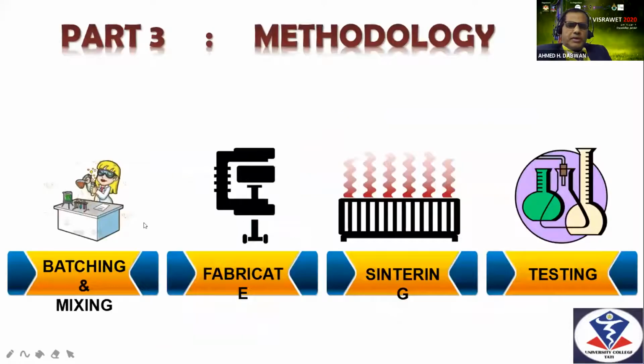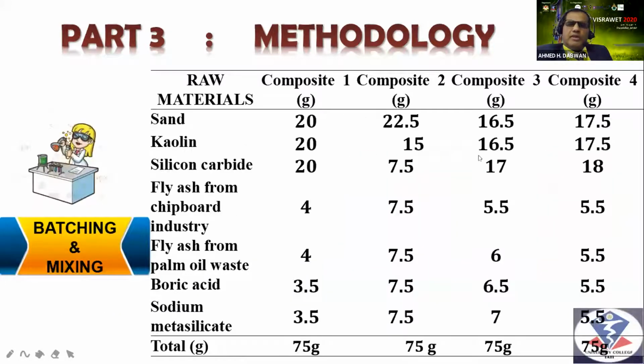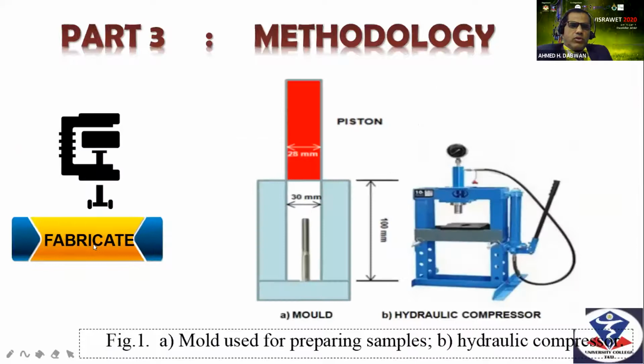What we did in our study, we take different materials like kaolin. I will show you the table later. Kaolin, sand, and boric acid, all these things. We use different weights, and we make the fabrication. Then we go for sintering, and then we go for testing. Those are the raw materials we use during our study. We do batching and mixing. You see here different ratios, the total is the same to see the difference. And then we go for fabrication.